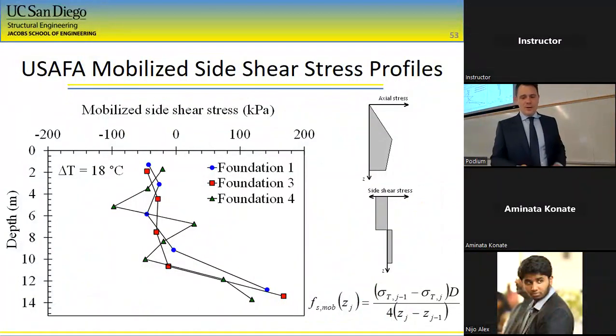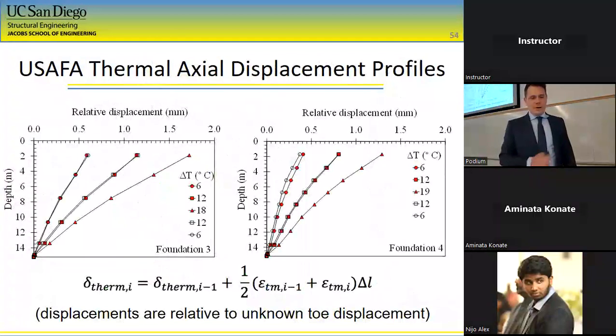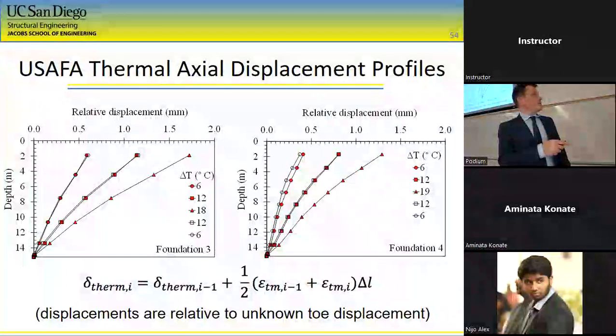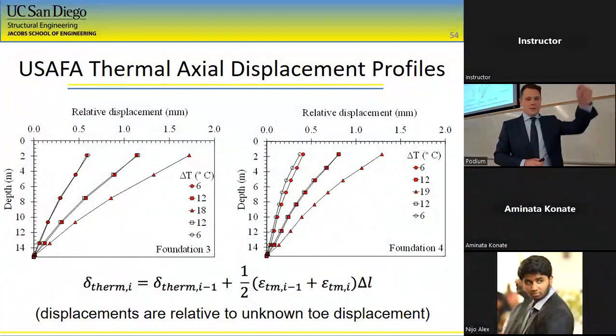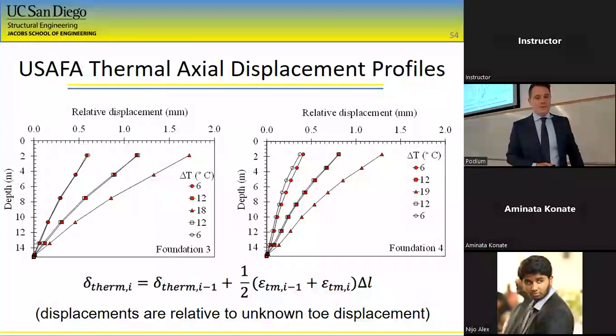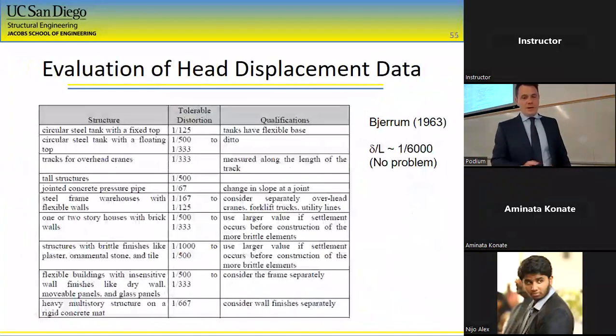We could also look at mobilized side shear with depth. We could integrate the strains. If we assume that there was no displacement at the toe, which is not the case, then we could integrate them with depth and get our displacement profiles. The nice thing about this is that we could figure out what the displacement at the top of the foundation would be for our highest change in temperature. And we could check that with respect to criteria for differential displacements.